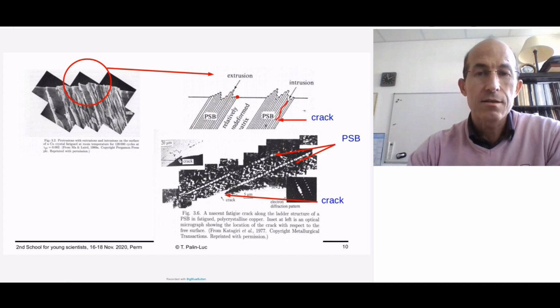And since under cyclic loading, of course, no material is created, if there is extrusion in some areas, in other locations there are intrusions. And these intrusions are the precursors or the locations of crack initiation. You can see here another picture. The surface is at the bottom, and you can see here the bands, and here the beginning of the crack, which is created along the intrusion.